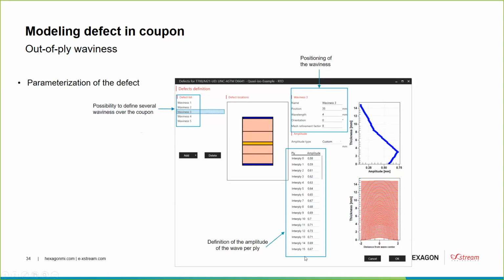In the most advanced one, we can define the amplitude of the wave ply by ply. So for each ply, we can enter the value of the amplitude of the waviness, and like this we can describe a very refined waviness. Then we can visualize here the profile of thickness through the laminate.